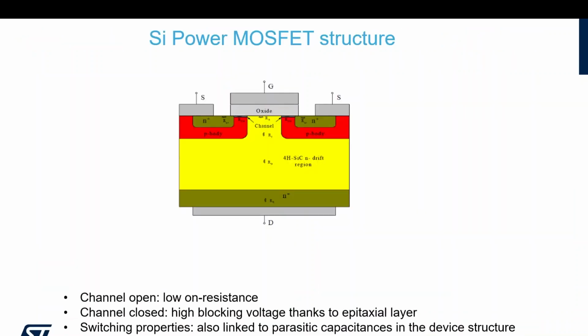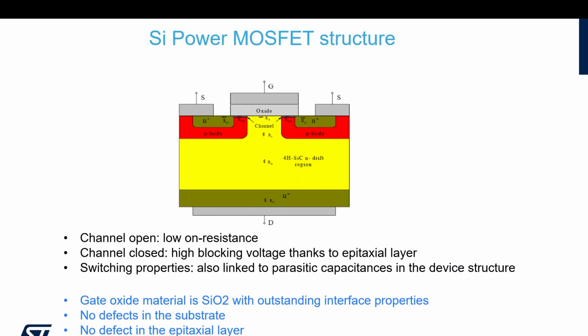So in a power device in silicon, you normally have a very simple structure, like a planar device in which you have your gate oxide, so you have your channel here. Basically you turn it on and off with the gate, the channel, and then you have a current flow from the source through the channel vertically to the substrate. That's how a power device works. So if the channel is open, you have a low on resistance. If the channel is closed, you have a high blocking voltage, because you use this thick epitaxial layer in order to withstand the electric field.